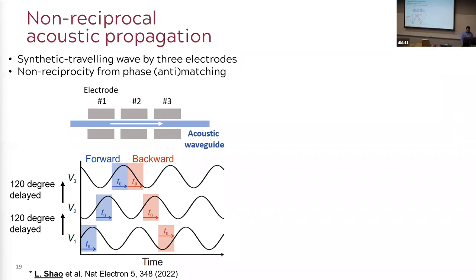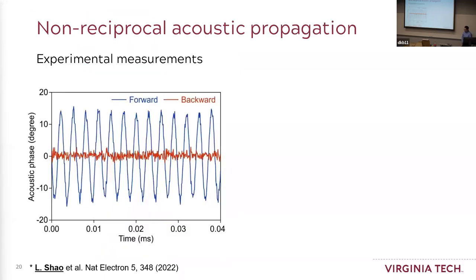That's how we achieve the non-reciprocal modulation of the acoustic wave. So here are some measurements. The blue line shows the acoustic wave propagating in the forward direction. It's being clearly modulated. And in the backward direction, it's not being modulated at all.